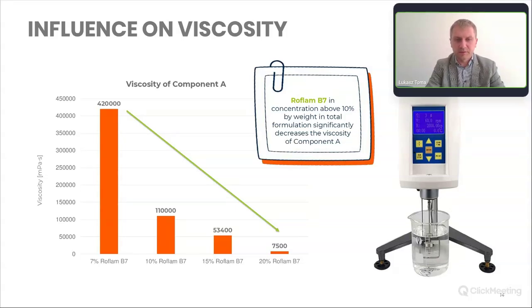Okay, so let's start with the viscosity of component A. This is an important parameter because a formulation with lower viscosity is easier to process, especially while you're mixing it with the hardener and applying it on different surfaces. So the tendency you see on this graph is quite obvious and clear for us. If we increase the content of Roflam B7, we can lower the viscosity. But take a look at the difference between 7 and 10%. We have a very significant drop of this parameter. So from my perspective, 10% of Roflam B7 is an appropriate optimum level to satisfactorily decrease the viscosity of component A.